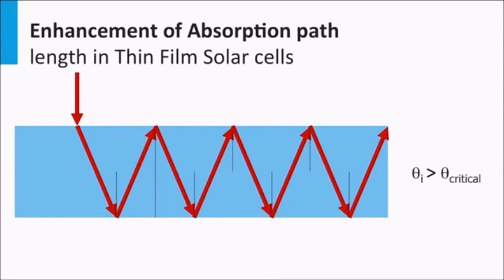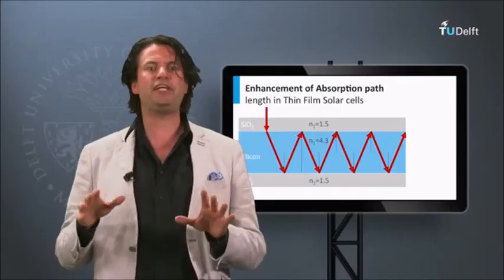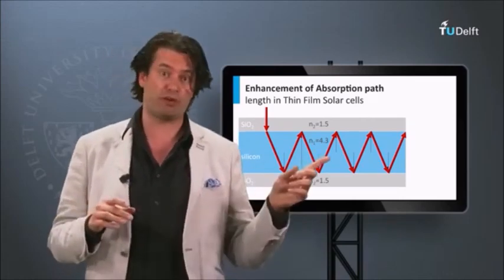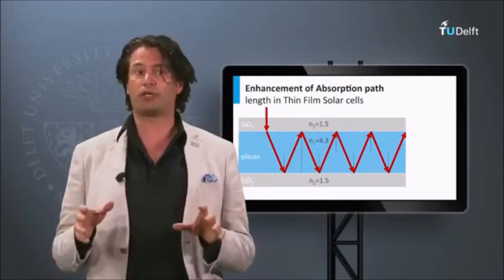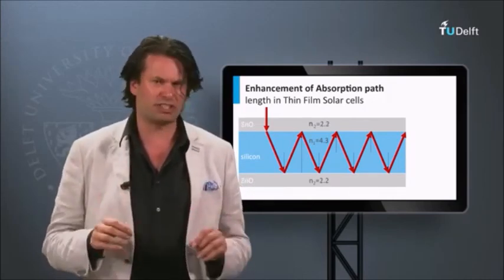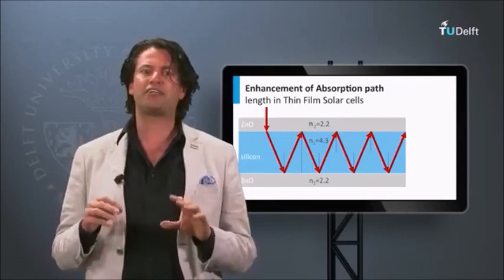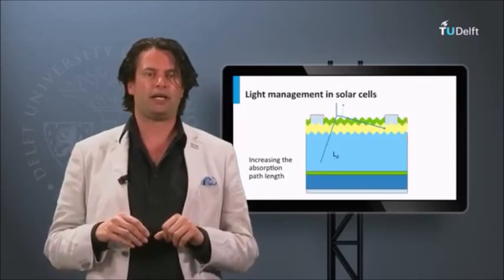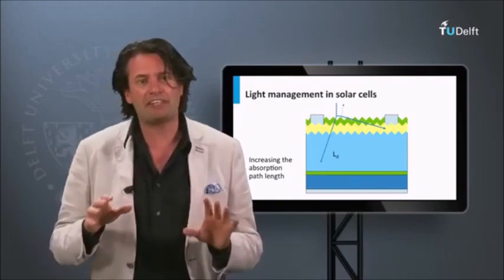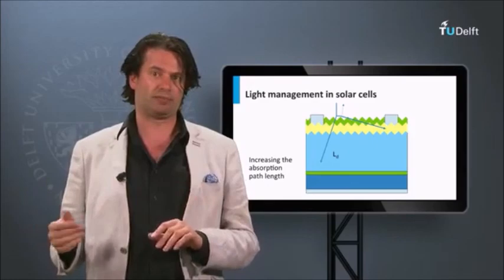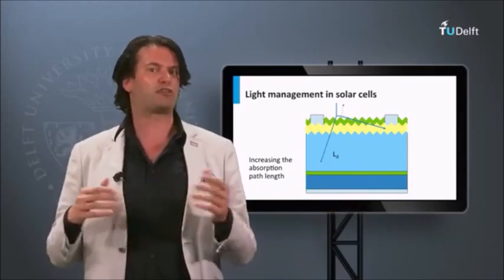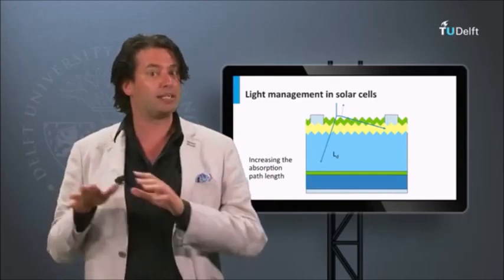The critical angle is a function of the refractive index of both media. If we consider silicon and air, this critical angle is rather small, 13.4 degrees. However, absorber layers are usually confined between supporting layers. If we would consider glass with a refractive index of 1.5, the critical angle becomes 20.4 degrees. If we consider zinc oxide, a typical transparent conductive oxide, we find a critical angle of 30.3 degrees. In the coming weeks, we will discuss various tricks to scatter the light on the angles into the absorber layer. Here you can see an example of scattering at microscopic texture, which enhances the absorption path length into the absorber layer.